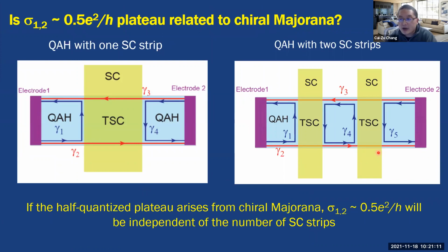This is actually a very simple control measurement. This is the structure I just introduced. If you put a superconductor layer here, this forms the TSC regime, the topological superconductivity regime. If you take the measurement between contact 1 and contact 2 and see the e squared over 2h plateau, it may be related to the chiral Majorana. But if we put 2 superconductor strips here, according to the theoretical prediction, it will form 5 Majoranas here, gamma 1 to gamma 5. When you take the measurement between contact 1 and contact 2, it should still be e squared over 2h. If you put 2 of them, it's e squared over 2h. That means when you observe e squared over 2h in the one-strip structure, it may be related to the chiral Majoranas.